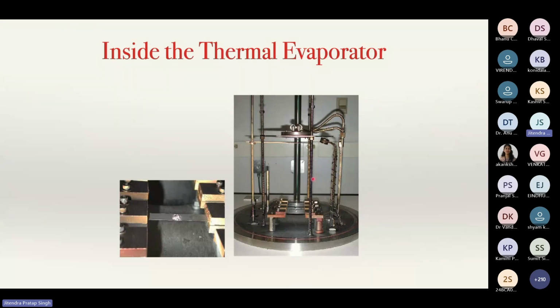Now, in case of E-beam, I am not showing the picture, but you have some kind of crucible, and the electron beam hits the surface. One of the advantages of E-beam over thermal evaporation is that in thermal evaporation this whole geometry gets heated up. The boat is heating up, and your material is also getting melted because of that. In case of E-beam, because it is a very dense electron beam, you can localize it on the surface and get localized heating. So your chamber or other material doesn't get heated up, and the contamination issue is less in electron beam deposition.